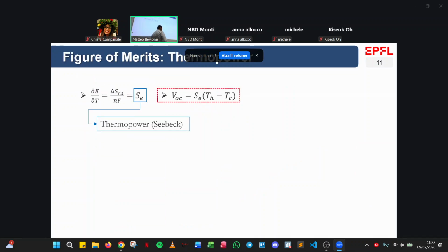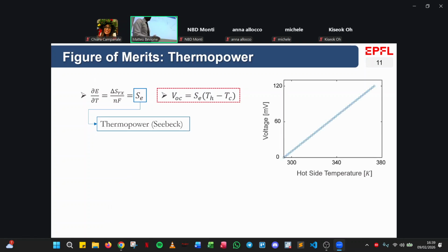In particular, there are two figures of merit that we need to introduce in order to know how these devices work. One is the thermopower, which here is indicated as thermopower Seebeck. Seebeck is the exact equivalent of the thermoelectric devices, but is defined as the variation of entropy of the redox couple we have in the electrolyte divided by a factor. And the beauty of this is that if we wanted to know what is the open circuit voltage we can actually produce, it's directly just the multiplication of the thermopower and the temperature gradient. So if we fix the cold temperature and we vary the hot side temperature, we will have this nice linear relationship between the voltage and hot side temperature.